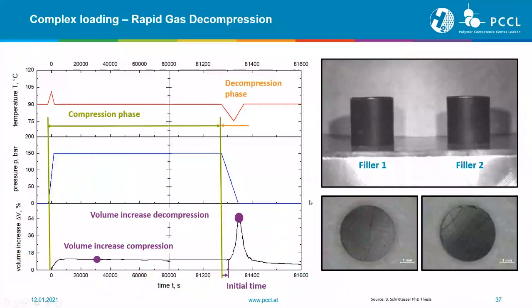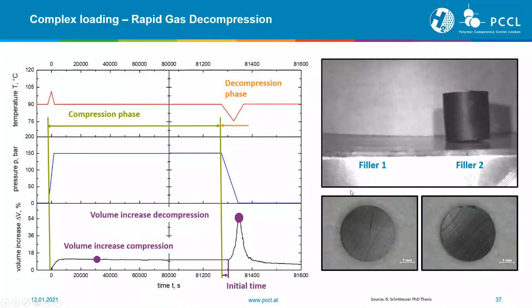And here I've brought with me a sample of 2 different fillers. So basically, more or less, the material is the same, just used filler A and filler B. And what we can see here now, the decompression phase starts, clear volume increase for both, but for one sample, the material cannot withstand this crack initiation process, leading to a rapid crack growth inside the material, and therefore you have like a rocket effect where the gas which is stored inside the material spontaneously is released by a crack, and the second material was very good performing with a ranking of 0.